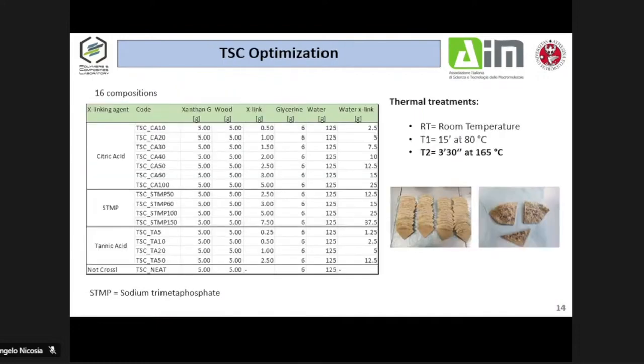So we optimized the composition. We added glycerin as a plasticizer to increase flexibility. We changed the type of fibers. We used wood fibers, longer wood fibers, to have a skeleton to reduce the shrinkage. And we tested different cross-linking agents, also sodium trimetaphosphate and tannic acid.